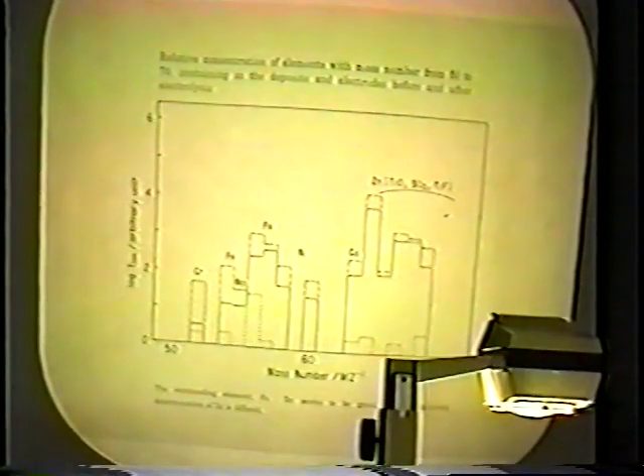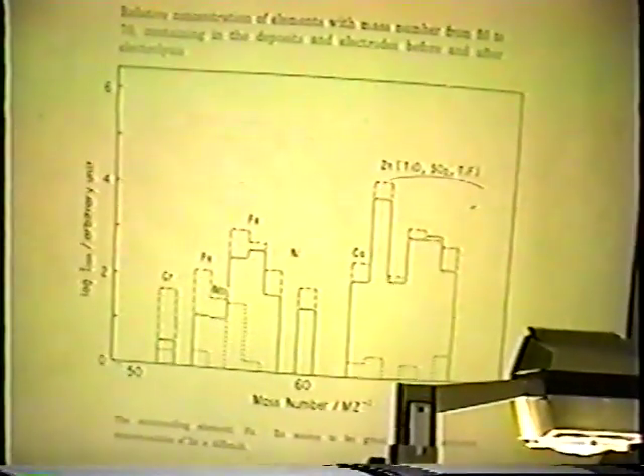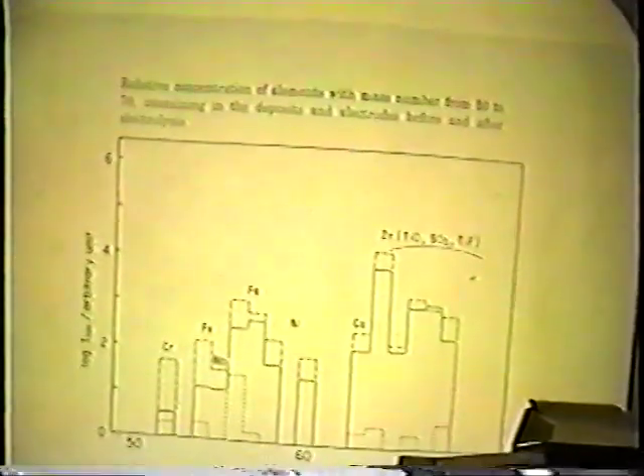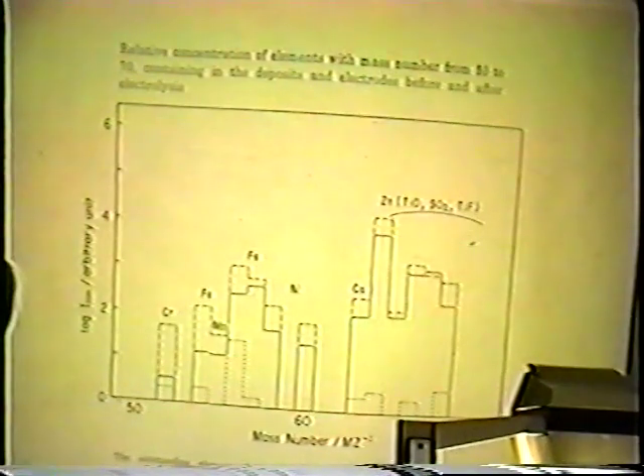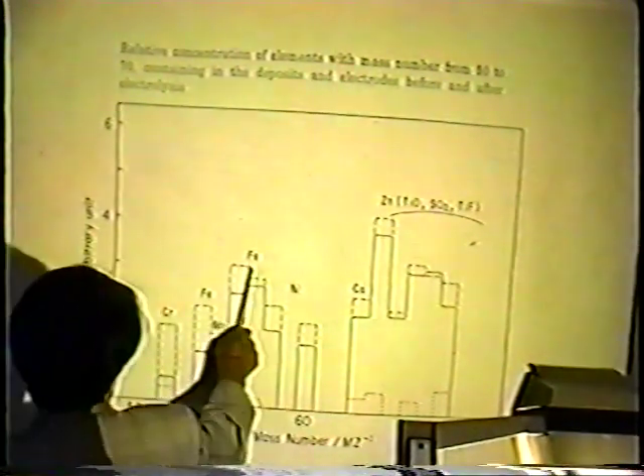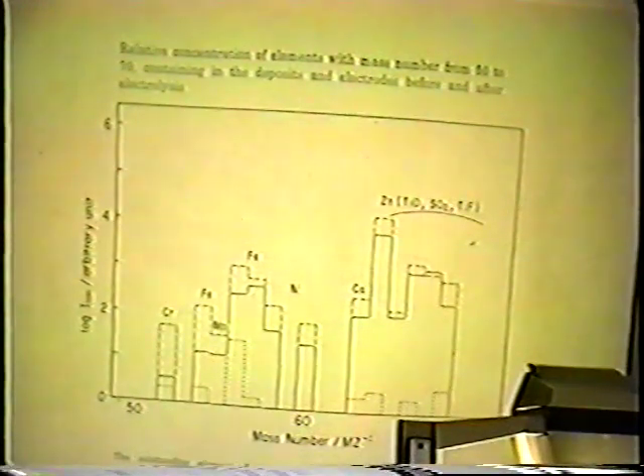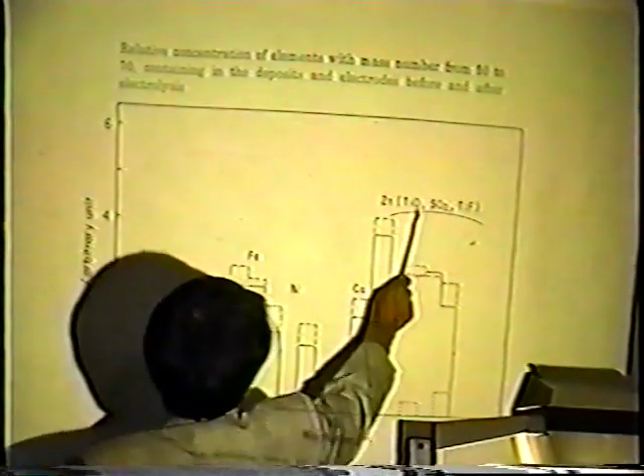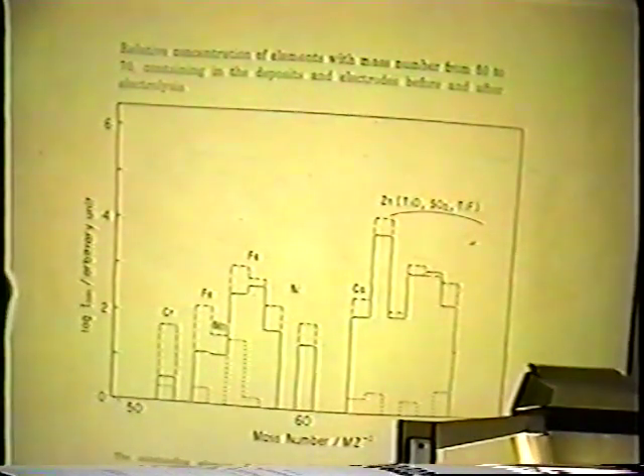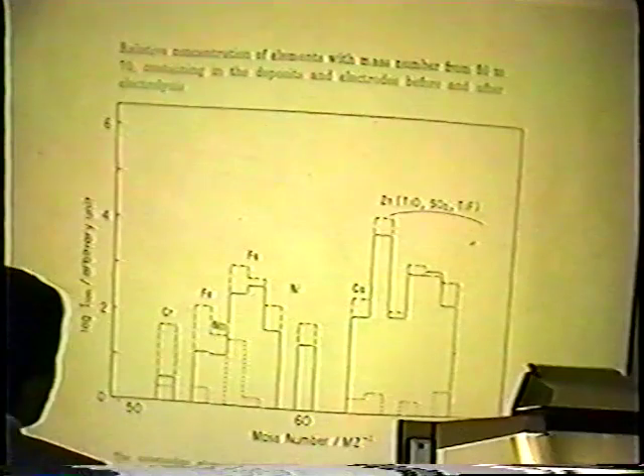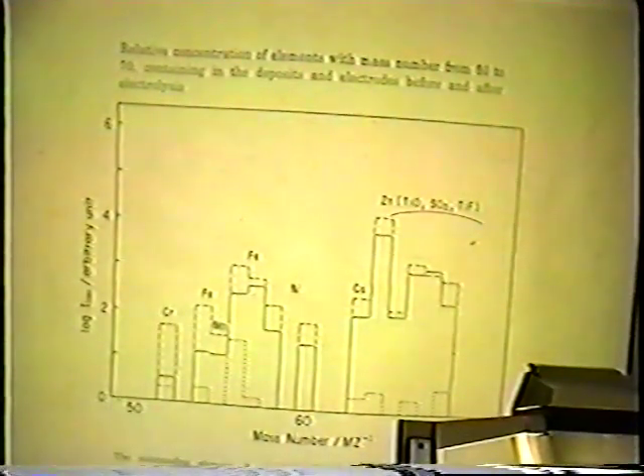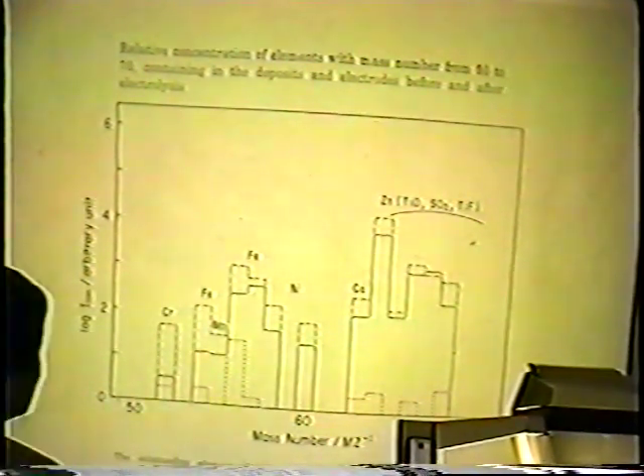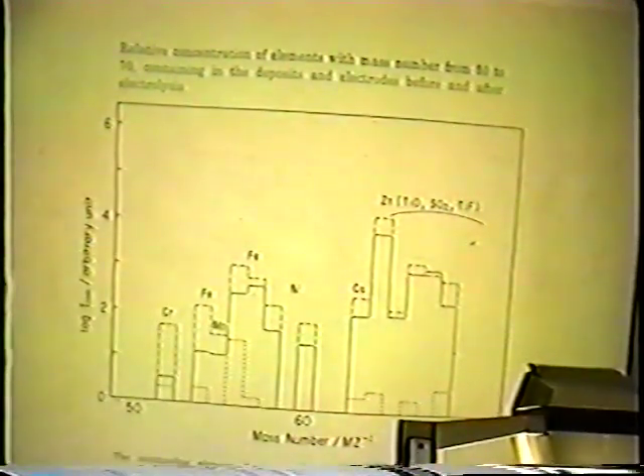The relative concentration of elements with mass numbers from 50 to 70 is shown in this figure. In this mass number range, the outstanding element is iron. In this figure, zirconium also seems to be great. However, in this mass number range, these particles overlap in signal, so accurate determination of zirconium is difficult. Perhaps the real concentration of zirconium would be smaller than this level.